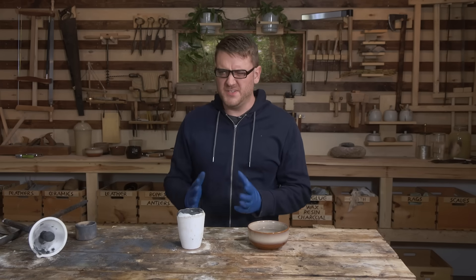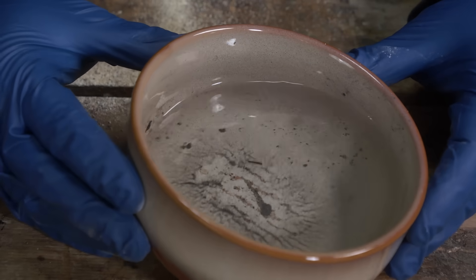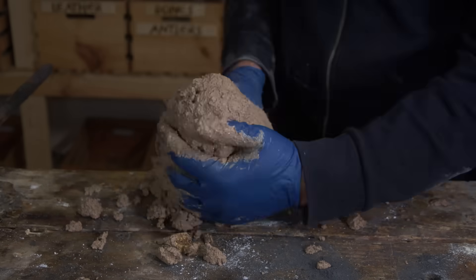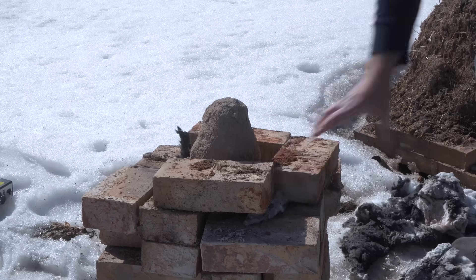This process was never really the most efficient — today we do electrolysis because it's much more efficient. That said, we do have something in the solution. We need a little bit better airtight seal on our crucible if we want this to work. So I'm going to try loading up the crucible again with more ore, and this time seal it with just clay.